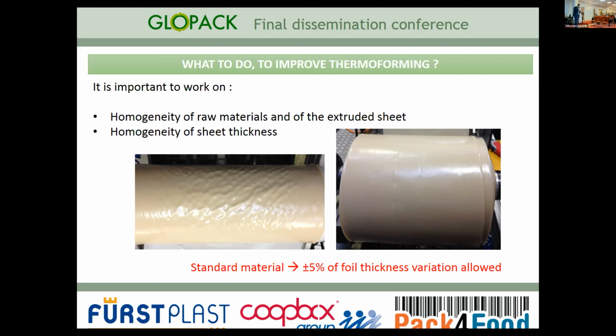The other point is the absence of particles that have different characteristics, let's say unmelted particles, because then the tray produced from that part of the foil will have problems, maybe some holes or other defects. This should be considered when we want to go to an industrial scale. As a comparison, for commercial standard materials like PET and PP, the variation of foil thickness is plus or minus 5%. This is generally accepted as a maximum, so we have to consider it if we want to scale up the production.